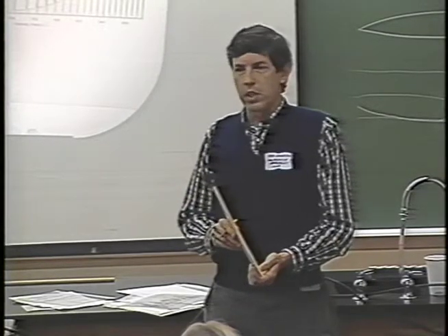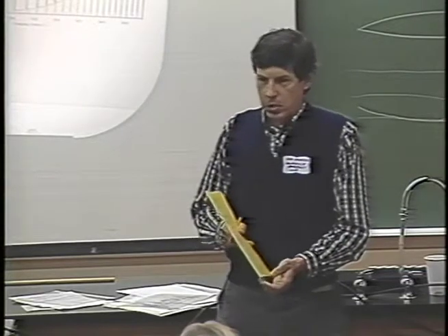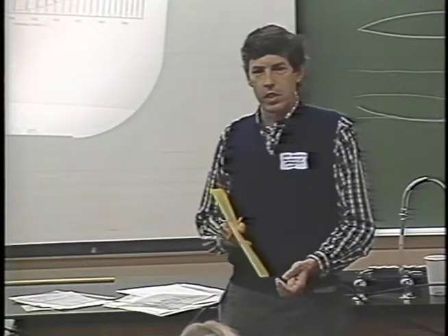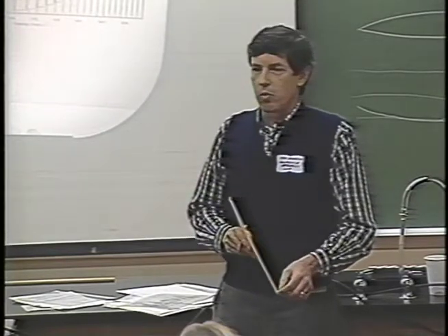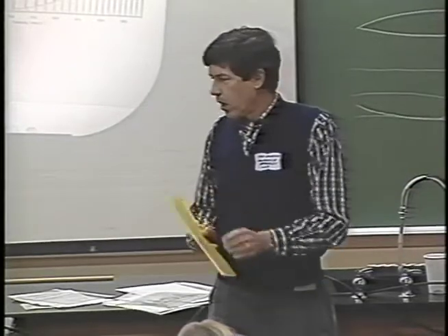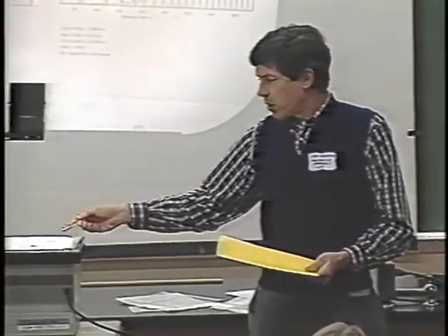And indeed, we like to work with specimens tilted up to at least 60 degrees. Now, what happens when you have a specimen tilted at that high an angle is that one end of the film is going to be way over-focused and one end is going to be way under-focused. And if you have a transfer function that varies from something like this at one end through something like this in the middle to something again that looks like this at the other end,